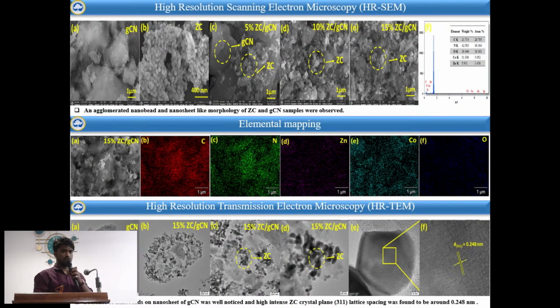These are the SEM images of our samples. Figure A shows the pure graphitic carbon nitride nanosheets, and B shows the nanobead structure of zinc cobalt oxide. This is the first time we have obtained this morphology with zinc cobalt oxide, which has not been reported yet. The remaining images show the composite formation of zinc cobalt oxide with g-C3N4. And we have also done the elemental analysis for the highest loading of zinc cobalt oxide in g-C3N4, showing the presence of carbon, nitrogen, zinc, cobalt, as well as oxygen.